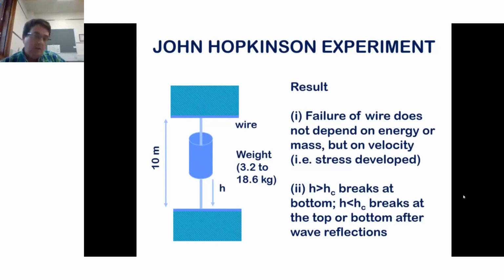And what he discovered doing these types of experiments on wires was the failure of the wire does not depend upon the kinetic energy or the mass involved, but it was very strongly dependent upon velocity. Yes, you could put a static weight on the system and break the wire. Absolutely correct. But if you're doing a dynamic loading, velocity turned out to be a key component.